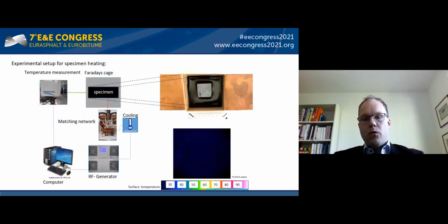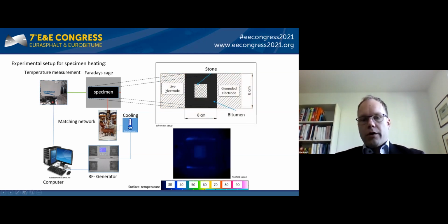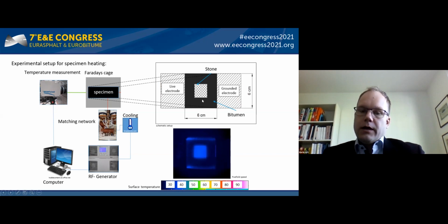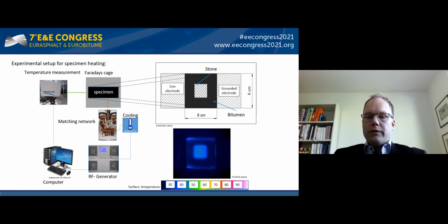So how will the radio wave heating heat up the asphalt? In a small experiment, it is shown that a stone is placed directly into bitumen and the radio wave heating will work through a radio wave generator connected to the specimen via a matching network, and an electromagnetic field will develop between the live electrode and the grounded electrode.